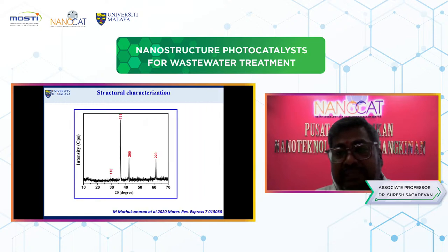the prepared sample was subjected to XRD, FESEM, FTIR and Raman analysis. First, we performed the XRD analysis. From the XRD pattern, it is very clearly seen that the peaks are well indexed, with the prominent peaks (111), (200) and (220). The planes indicate the copper oxide has a cubic structure, and the material has high crystallinity, because you see that the intensity is very high. In addition, no impurity peaks are observed in the XRD pattern, which confirms the crystal structure of this copper oxide as cubic.